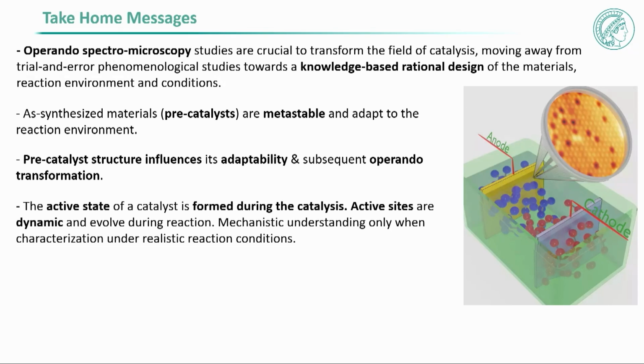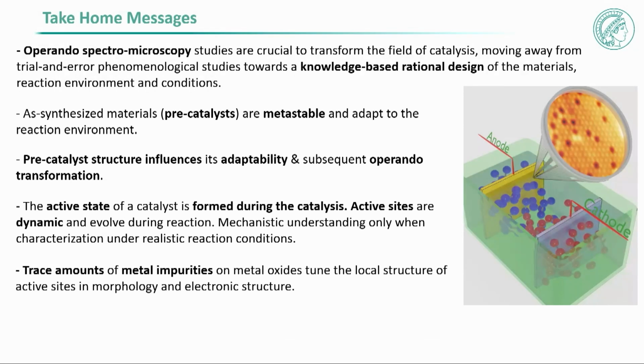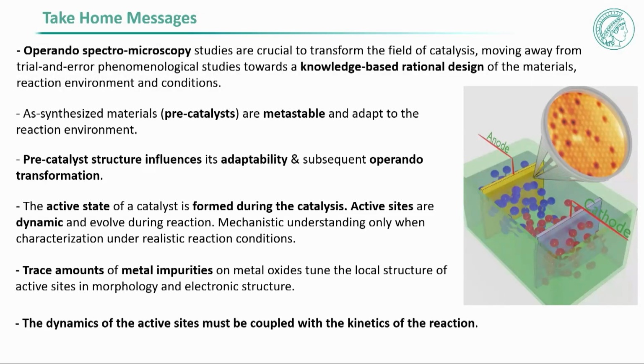Because the active state of the material is only formed while the material is operating. The active sites are dynamic. I hope that I could show you this even with videos. And if you want to get mechanistic understanding, then you need to really be looking at the material while it's performing the catalysis. With the example of iron, I tried to illustrate that very small amounts of metal impurities on these metal oxides tune the local structure of the active sites in morphology and electronic structure, and also that the dynamics of the active sites must be coupled with the kinetics of the reaction.